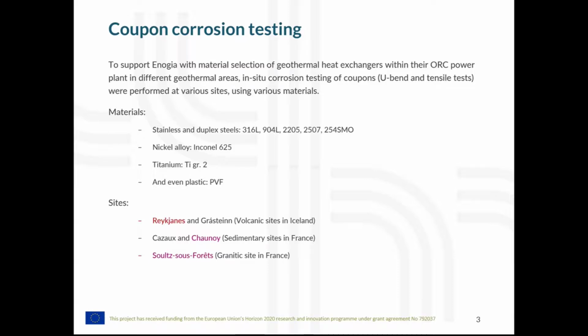and evaluated which materials were performing the best. And as you've seen, we mostly focused on stainless and duplex steels, but we also looked at Inconel 625, which is a nickel alloy, titanium grade 2, and even plastic. And the initial coupon corrosion testing, for the initial material selection of the heat exchangers, was performed at Reykjanes, Grásteinn, and Cazaux. And then later in the project, we also did some coupon testing at Chaunoy and Soultz.